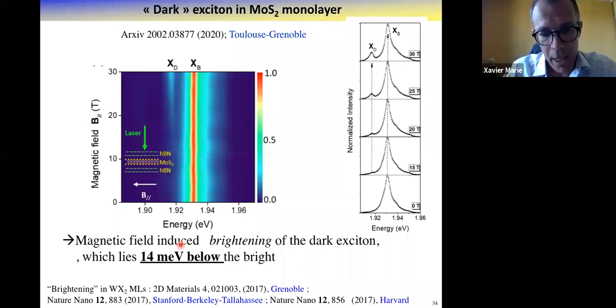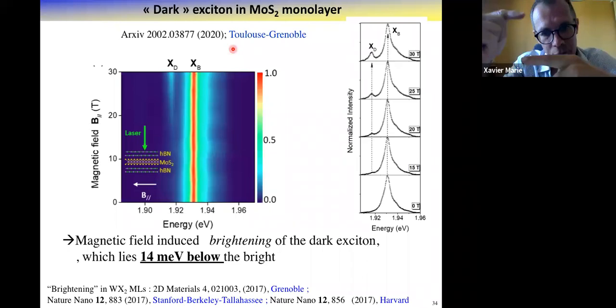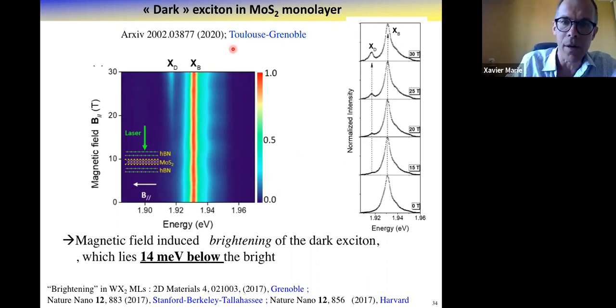And this approach is fully consistent with what we found for WSe2, WS2, and also recently for MoSe2, which Smirnov measured in Tallahassee less than one year ago. And in this work, we did it also in MoSe2. So we find MoSe2 just 1.5 millielectron volts above, though the spin-orbit splitting in the conduction band is much larger. But then it decreases the splitting between bright and dark with the two other ingredients: conduction band mass and exchange energy.